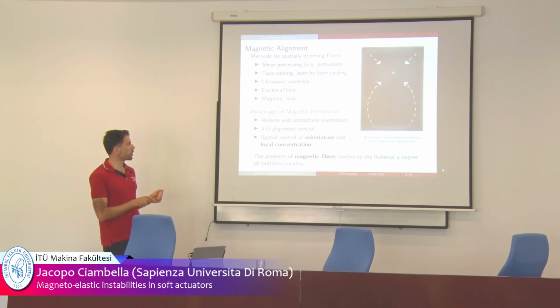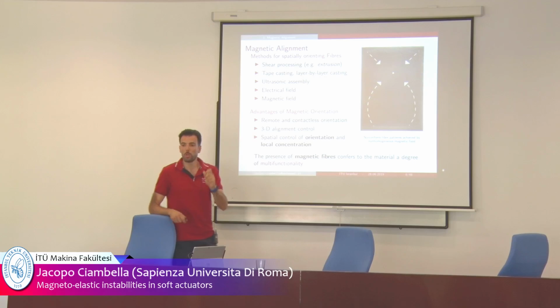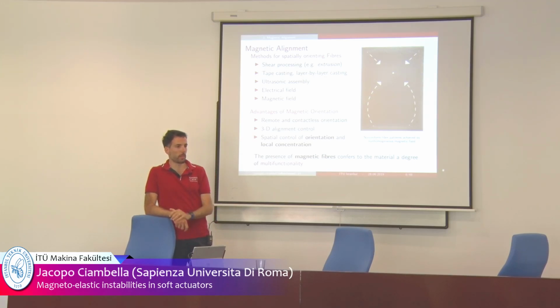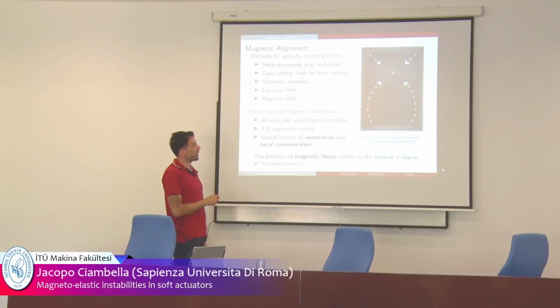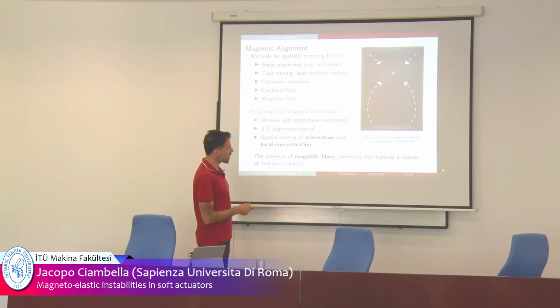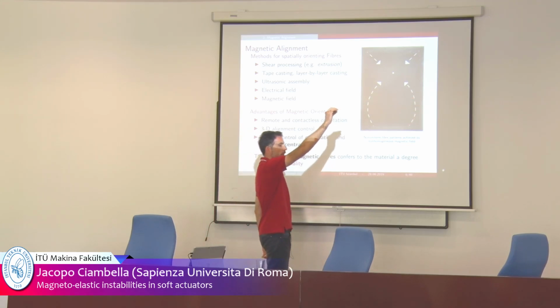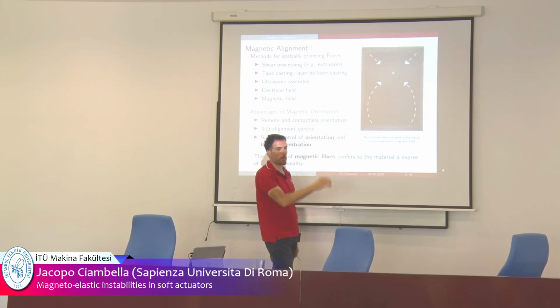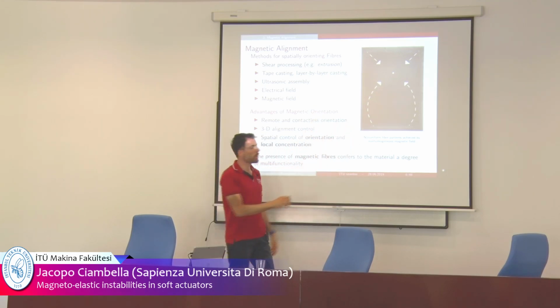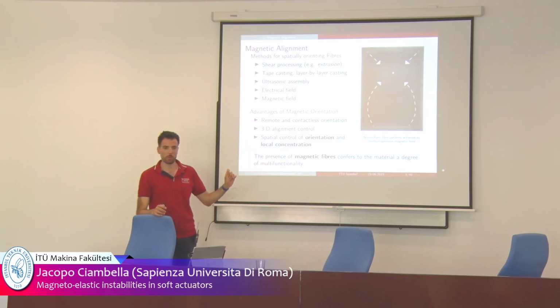And also you can achieve very complex shapes, because if you use nonlinear magnetic fields, which are very easy to generate, imagine the magnetic field generated by a cylindrical magnet. A very simple cylindrical magnet generates a nonlinear field, where the field lines change with space. And this is exactly what is done here. You can't see very well, but this is a specimen where the cylindrical magnet is underneath this point, vertically aligned. And then you see that the fibers initially are bent over the plane and then start rotating towards the magnet. Okay, so around this region they are vertically aligned, so they are going out of the plane of the projection. In this region they are aligned within the plane of the projection. So you can simply obtain very complex fiber patterns with the magnetic field.